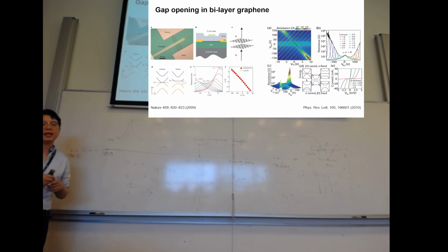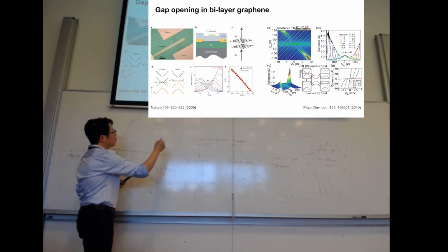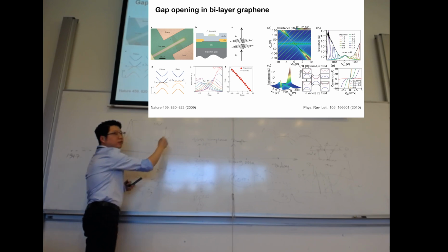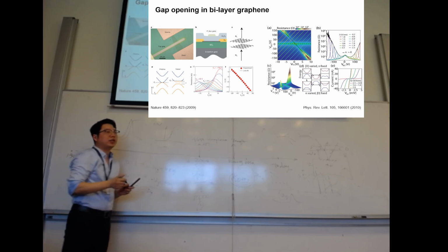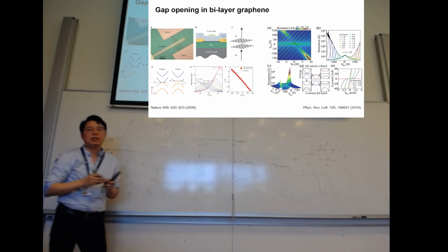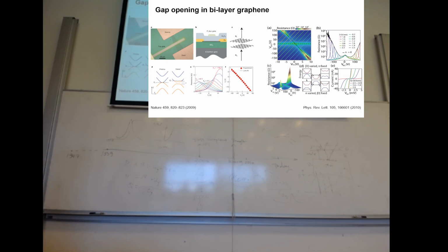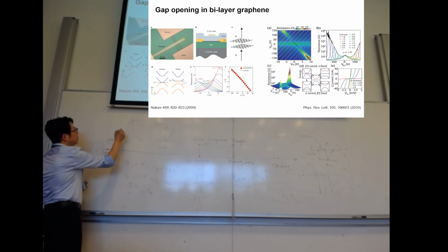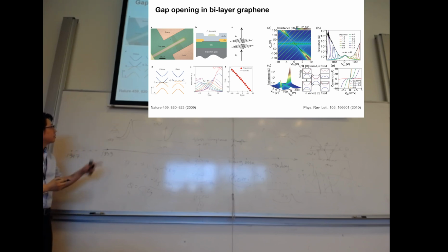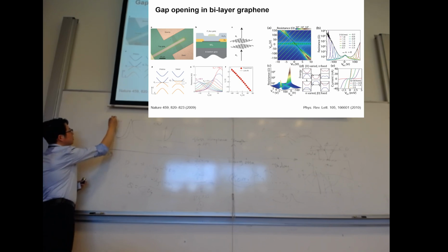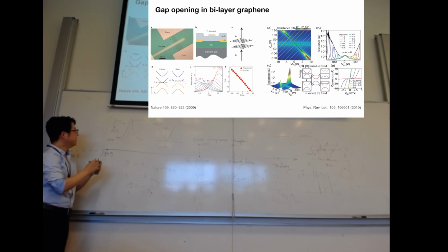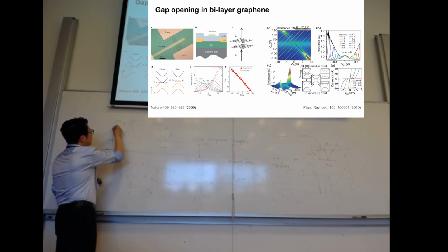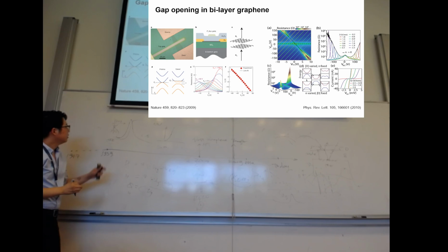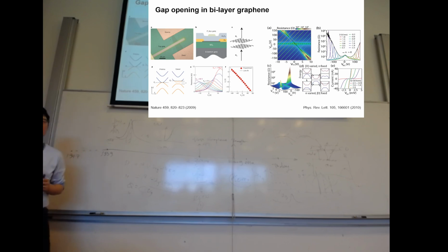A very good transistor should look like a step function, the ideal ones. And that's actually what people obtain in silicon transistors. They're very good. If you look into these commercial ones, their curves rise really rapidly in a very small range of voltage, and you obtain saturation current. Here it's really off. The on-off ratio can be 4, 5, 6 decades. For graphene, if you don't have a gap, here you are in this valence band, you have holes. At this point, you are at the minimum of the density of states. This is DOS. It looks like dispersion, but it's DOS, okay. And then after this one, you are entering this conduction band. So you are conducting again. That means if you want to use graphene as the on and off, the off is only here. It's very narrow, cannot control that.